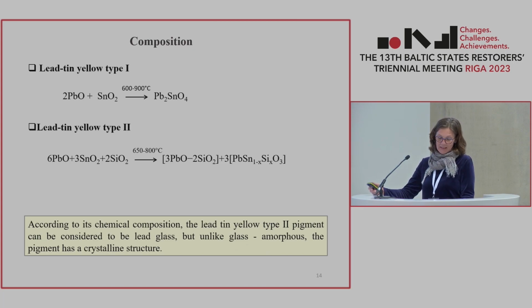When mixtures of lead and tin oxides are heated, it results in lead tin yellow type 1 pigment that has orthorhombic forms. Lead tin yellow type 2 pigment is obtained by heating a mixture of lead tin oxides as well as quartz and has a crystalline cubic form. Lead tin yellow type 2 pigment, according to chemical composition, can be considered as lead glass, but unlike glass, which is amorphous, the pigment has a crystalline structure. This allows for successful identification by XRD and Raman spectroscopy, even if it is in a glass as matrix.